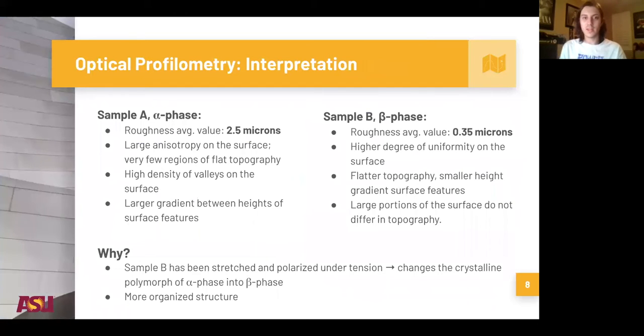So sample A, like I said, is alpha phase, and from the images generated from the testing, we got a roughness average value of 2.5 microns. We can see from the images that there's a large amount of anisotropy on the surface, very few regions of flat topography. The beta phase, sample B, had a roughness average value of 0.35 microns. It's much more uniform on the surface, much flatter topography.